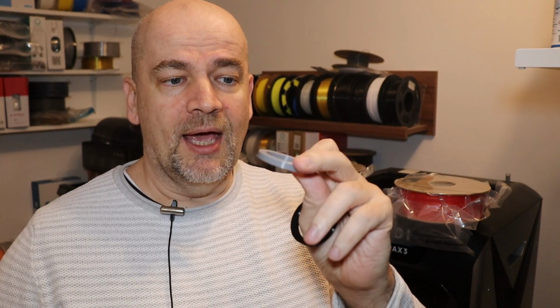Maybe two properties I could mention here because they are important for me, and that's the layer adhesion, and the Qidi was better in this case. And the second is that I experienced a little bit more stringing when I printed with the BambuLab TPU filament, and I believe that the reason for this is the higher viscosity at these temperatures because it can be printed at higher speeds too.